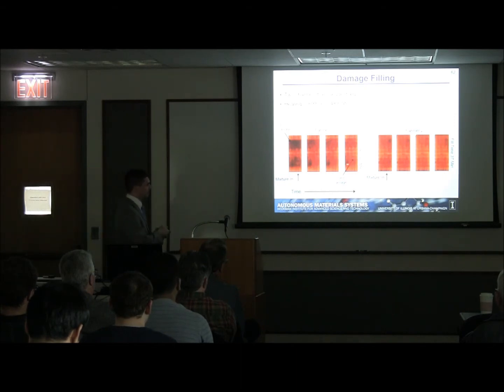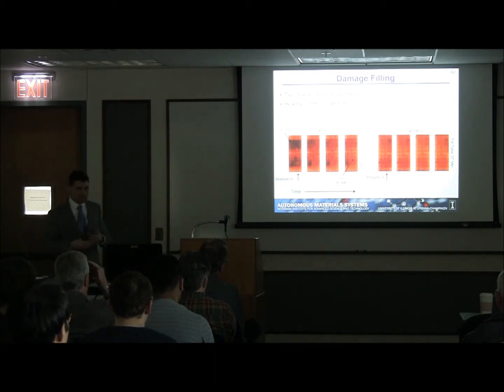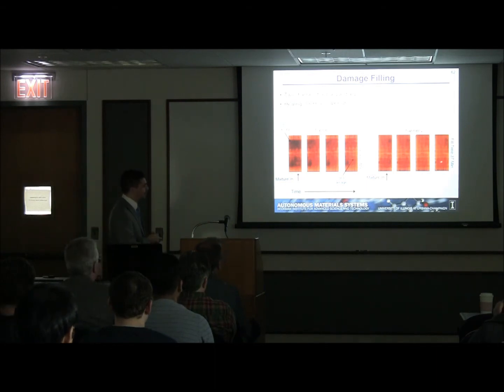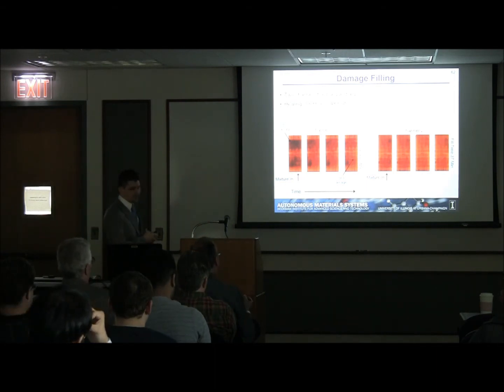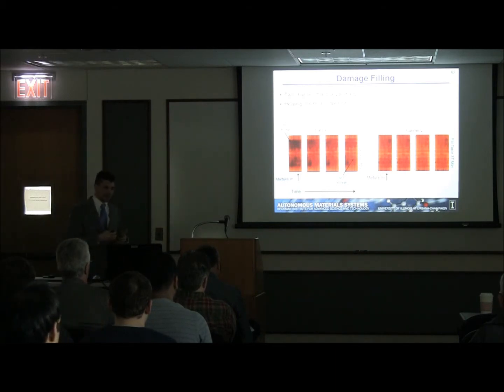Then you can imagine this sample is flipped 180 degrees, and now we're coming in on the opposite channel. Again, the piercing point is roughly in this location, where it goes down to the sample, and then we start to see increased optical matching, indicating that we filled some of the damaged regions. What's interesting to note is that even in these particular situations, not all of the damage is filled. We think that this has something to do with the damage connectivity in the material, and I'll discuss a little bit more about that when we get to some of the cross sections of the material.